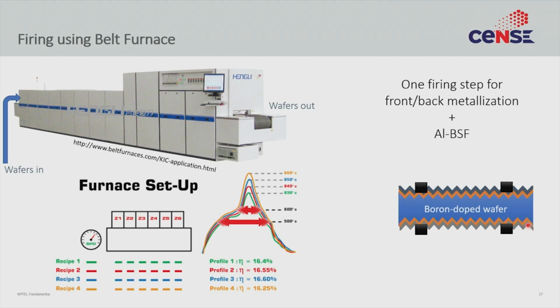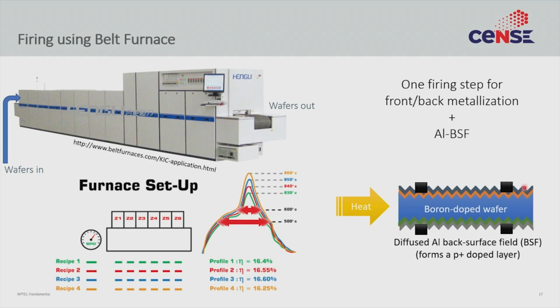Okay, so you do that, and when you do that, the aluminum back surface field forms in the back, and that is how you get rid of the n-type or the phosphorus doped layer in the backside. You just override the phosphorus doped layer with the aluminum doped layer, which is a P+. So you have the P+, you have the P layer, you have the N+, you have the silicon nitride on the top, you have the aluminum on the bottom, you have silver contacts. Done. So that is how a commercial silicon solar cell is made. Okay.